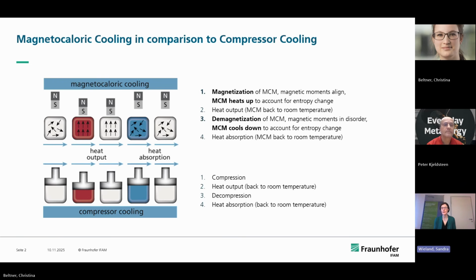By this, the entropy changes. The entropy goes down when something is aligned. But in this case, if you say the entropy is constant, then to account for this change in entropy, the temperature goes up. So the material heats up to keep the entropy constant. And the material is getting warmer. And more or less the same thing backwards is happening when you take the material out of the magnetic field. The magnetic moments de-align, and to keep the entropy constant, the temperature goes down.